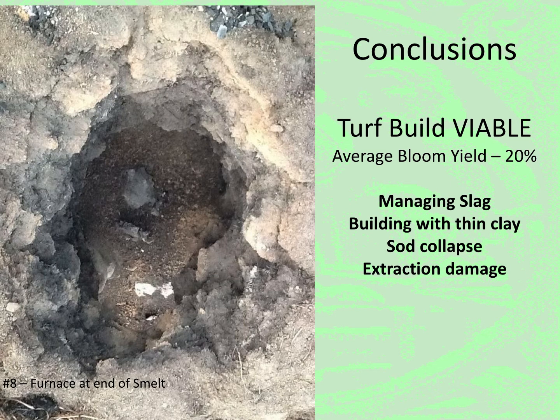That being said, it remains obvious that still more experience is needed with this furnace type. Managing slag collection, especially in combination with certain air insertion types, remains a problem. It was found as the clay liners got thinner and thinner, it became more and more difficult to get the clay to physically remain in place against the fragmenting sod walls. It was certainly found that without a protective clay liner, the grass sods would collapse in the inner surface at the end of the smelt especially.